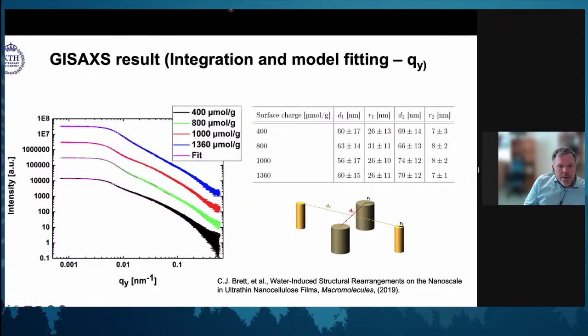If we were doing this with X-rays, we can still do the characterization, but the X-rays will not make any difference between the water and the cellulose, in principle. Cellulose is very close to water, except there's a carbon atom for every water molecule. So it's very hard to differentiate between the water and the cellulose. So what we did was choose to try to do this with neutrons.